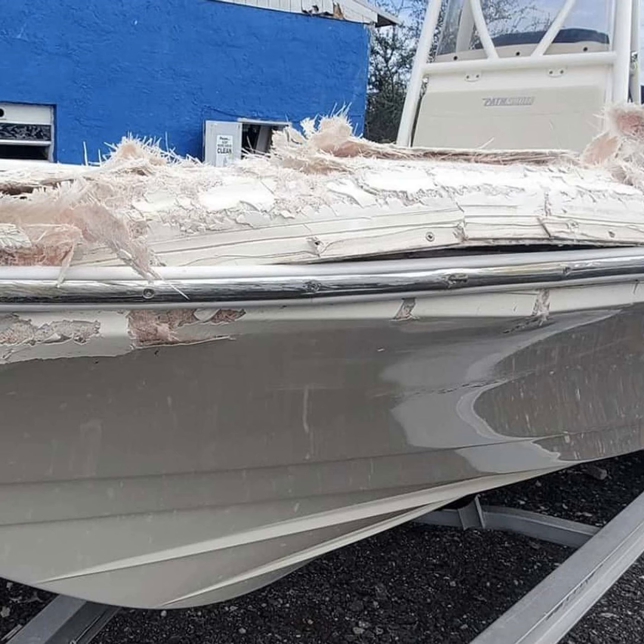enough, but you leave too much glass on, a lot of the times one of the mistakes of not grinding enough in the beginning is that you also don't grind enough afterwards. So what happens then is you didn't take enough glass out the first time, then you applied too much glass, and then you grind over that glass to try to smooth it down, and you didn't take enough of that off either. So now you're definitely going to have a hump. And you just got new glass over still damaged glass. So one of the things that I like to do, let's just keep going with this 6-inch hole example.